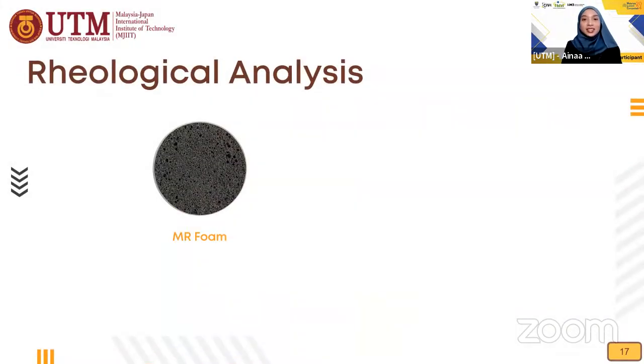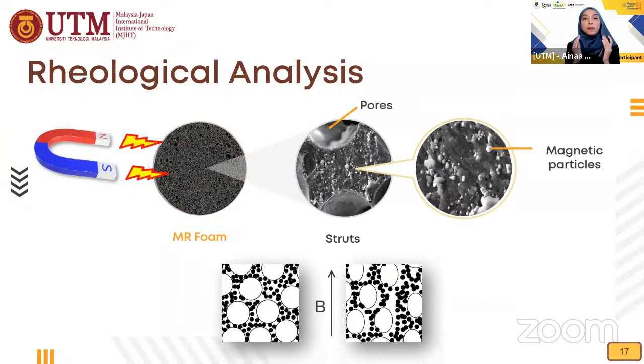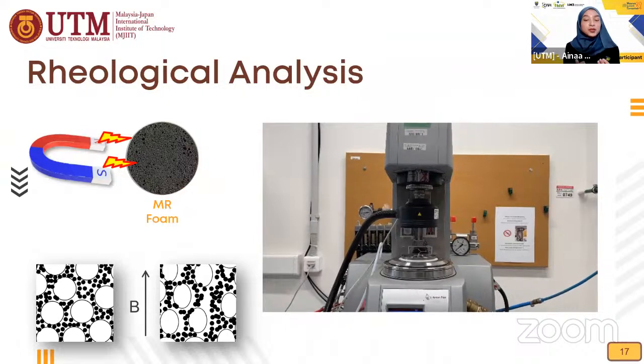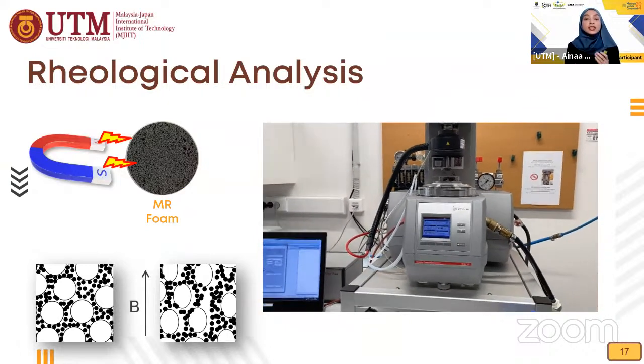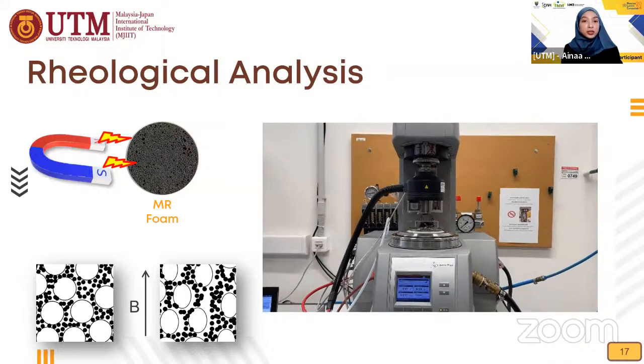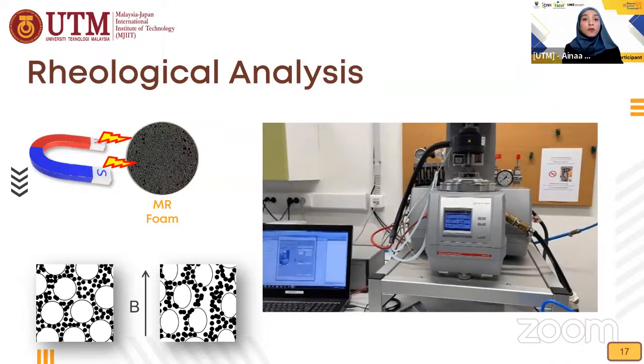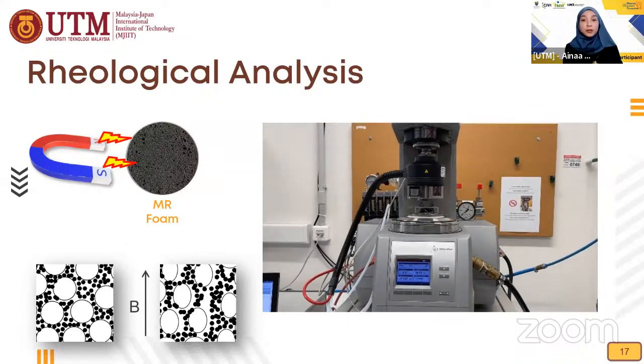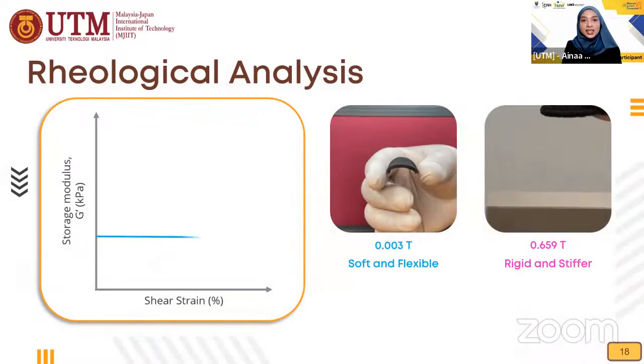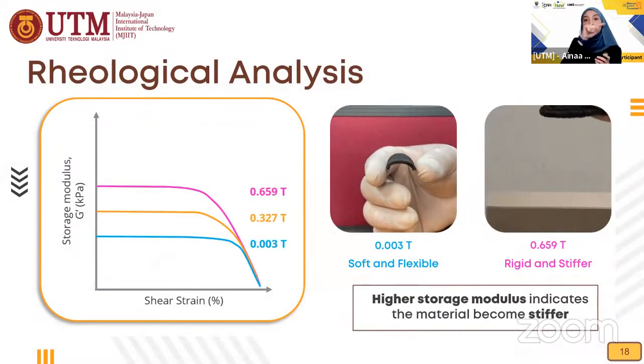The second characterization is rheological analysis. When magnetic field is applied to MR foam, the pores tend to elongate as the result of the reaction of the magnetic particles towards the magnetic field. These changes can be analyzed using a rheometer, where it is commonly conducted under the presence of magnetic field. It is important to conduct this analysis because the behavior of MR foam varies depending on the strength of the magnetic field. From this analysis, we can observe that the higher magnetic field we apply, the higher storage modulus we could achieve. Or in other words, higher storage modulus represents that this material to become more stiffer.